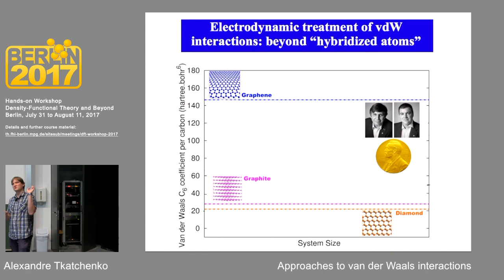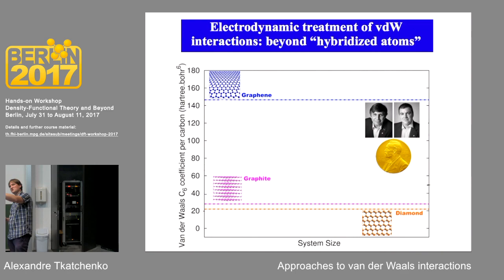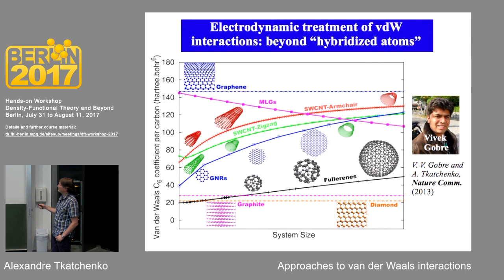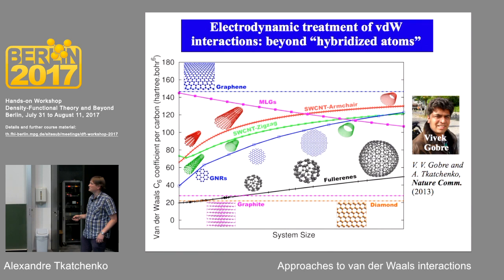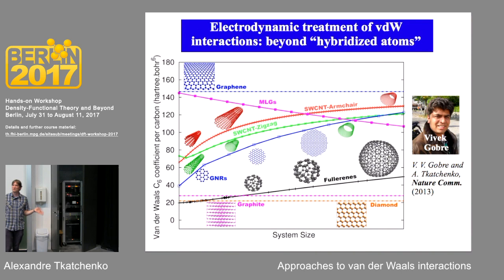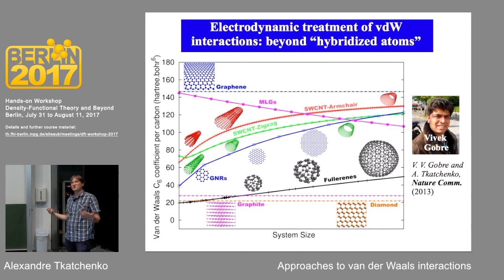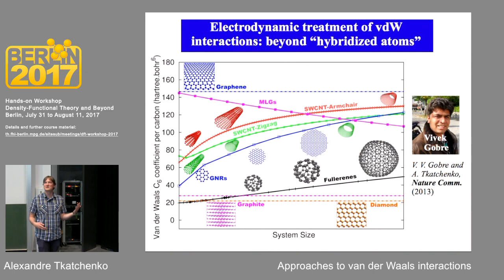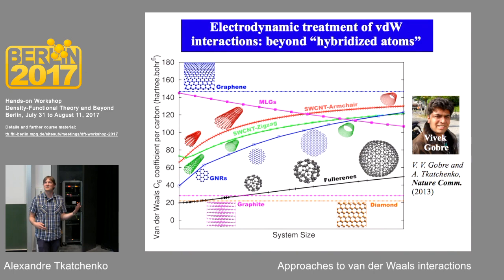In graphene, all electrons can only polarize in-plane — no out-of-plane polarization — so the in-plane polarization is extremely large, causing C6 coefficients to scale non-linearly. Applying this to nanotubes, nanoribbons, and fullerenes, the van der Waals C6 coefficient ranges between 20 and 160 — an order-of-magnitude change from dimensionality and geometry effects beyond any chemical hybridization. These long-range many-body effects make van der Waals interactions non-additive and enable control of self-assembly through dimensionality and geometry of carbon nanostructures.